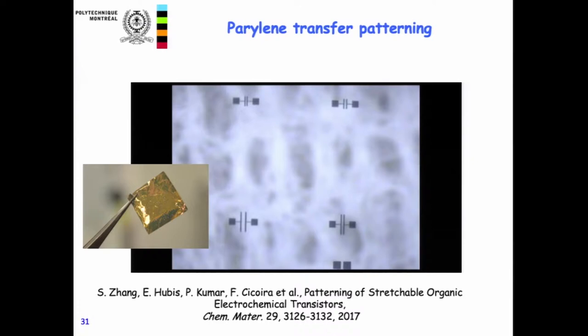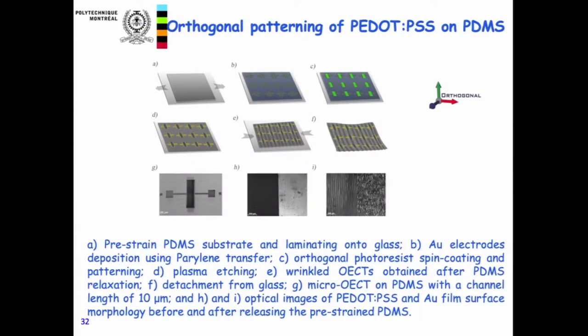OK, so this step is the metal deposition, and the following step is the conducting polymer deposition and patterning, which is done in the same way that I showed for the flexible substrate, so orthogonal lithography. At the end, we get some devices like this. So you see here, this is the gold, and this dark part in the middle is the conducting polymer.